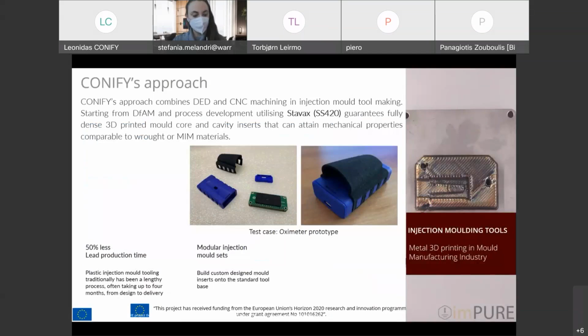CONIFY's approach is, as mentioned earlier by the other panelists, a hybrid approach. So what we're trying to do is to combine direct energy deposition, CNC machining and injection mold tool making. We start from design for additive manufacturing, and we did our own process development and material development in-house in order to process stainless steel 420 that guarantees a fully dense 3D printed mold core and cavity inserts that can achieve mechanical properties comparable to wrought or metal injection molding materials.